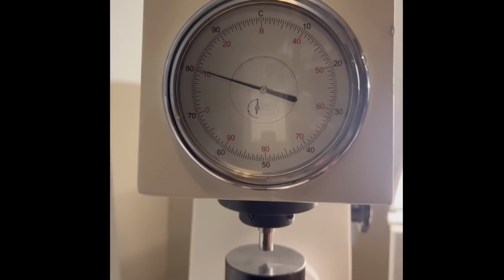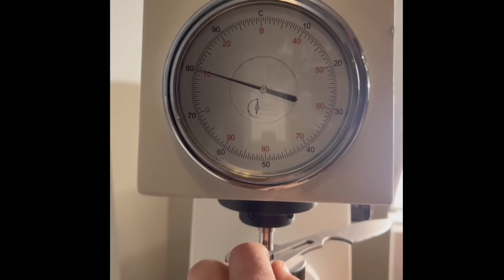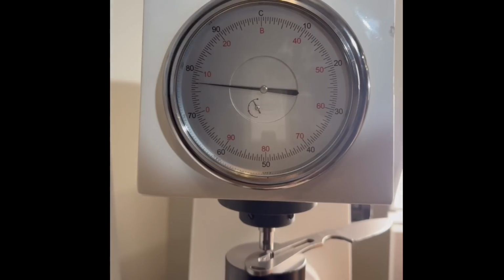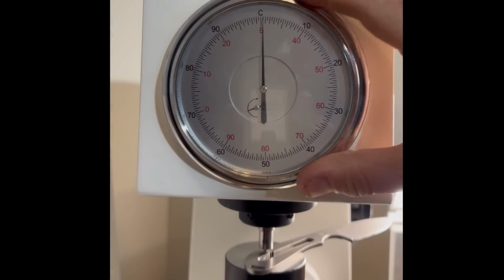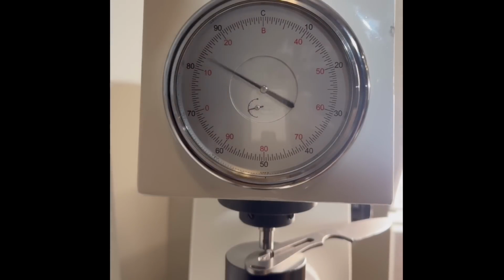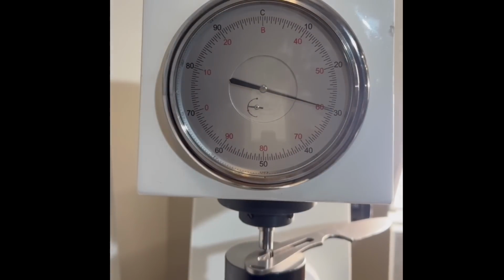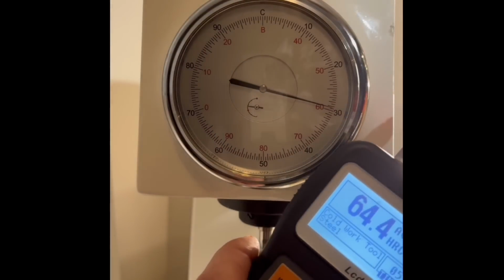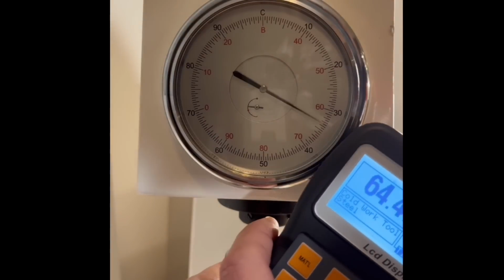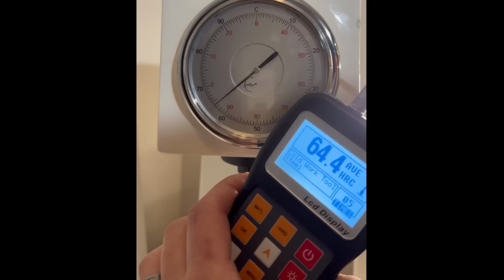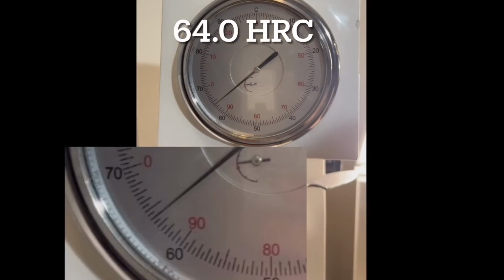I continue by moving the camera back to the benchtop and placing the blade under the probe. And by the way, the video speed is 2x for this segment. The benchtop Rockwell tester calibration video came out recently, and it gets into a lot more detail on how this device operates. I'm holding my breath for 64 plus or minus 1/2. 64 spot on. Unfortunately, not always.